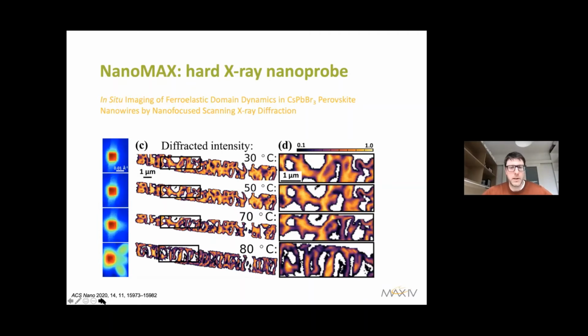The scientific example shown here is quite interesting because this is a study of phase transformation in a nanowire. And this particular nanowire is a perovskite nanowire, which is useful for solar cells, for example. However, nanomaterials, in particular nanowires, are also quite interesting morphological systems for catalysis. It's very relevant for catalysis as well. So what's been done here is X-ray diffraction, by scanning the beam through the wire. Here you can see, I hope you can see my laser pointer here, this is the nanowire, and every pixel here represents an X-ray diffraction image, and the sum of all of them is shown on the left-hand side. This is the sum of all the diffraction images through the whole wire.